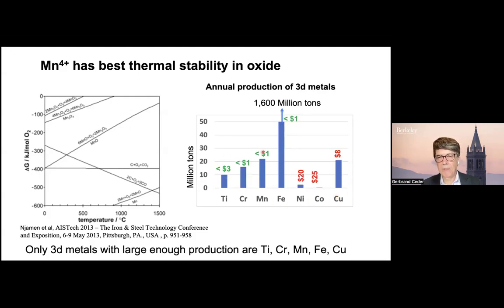I've listed here roughly the price of the precursors, either the metal or the oxide precursors. And of course, copper has been challenging to work as a redox couple, because of the different valence states, which prefer extremely different coordination. So it's very difficult to do intercalation chemistry with copper. And then titanium is kind of low voltage, that's why we use it on the anode side. So we basically have chromium, manganese, and iron.